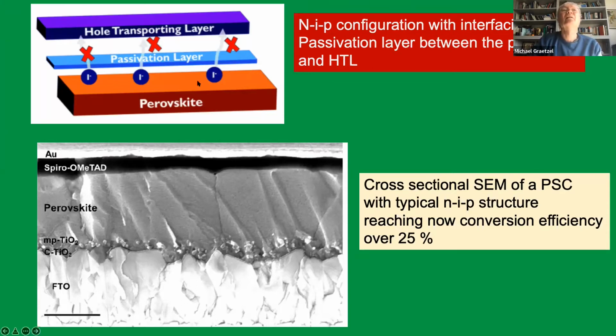Today, let me say a few words about the leading research. A lot of people focus on passivation layers. You see the following issue is being faced. The perovskite itself is an ionic crystal, very polar, and dissolves in polar solvents and in water, for example. Then you have the hole conductor, which is not polar at all, so this interface needs a surfactant to match the two polarities. So you put this passivation layer in between the hole transporting layer. See here, this blue part is the passivation layer. That's a molecular layer that matches the polarity of the perovskite with the hole transporting layer.